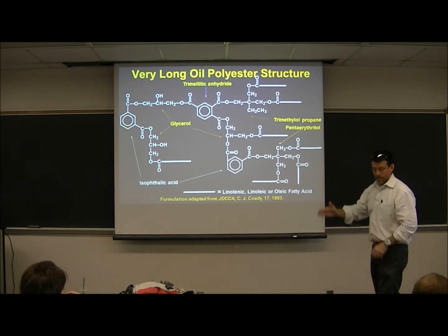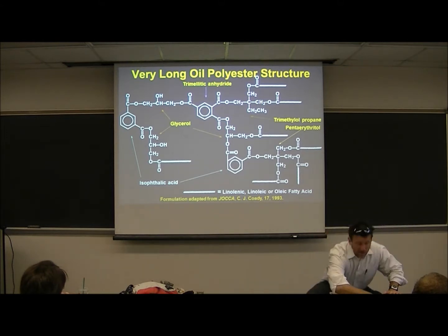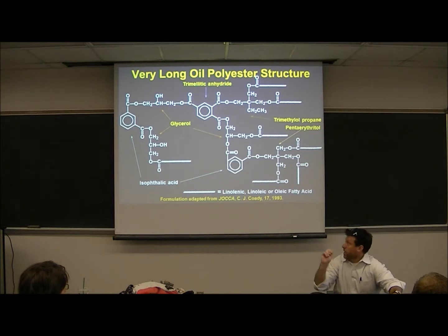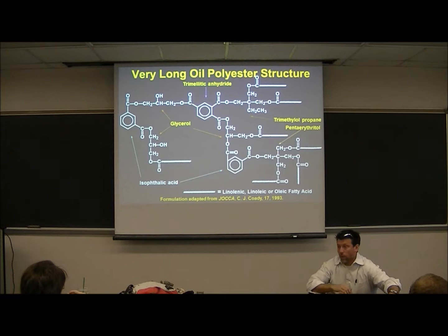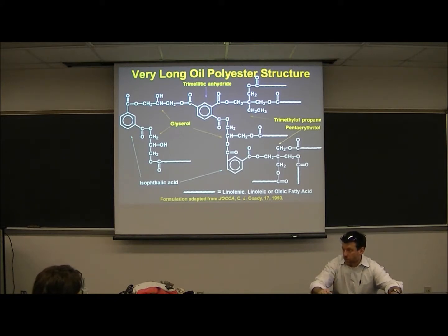This would be cast as a film. It was an excellent film former. It would form smooth, thin films, even at 100% solids, because of the low viscosity and low molecular weight. And then it would auto-oxidize without any other catalyst. It would take probably 24 hours before it was tack-free. It'd be sticky at first, and it would become tack-free. It's a usable product as finished for certain applications.